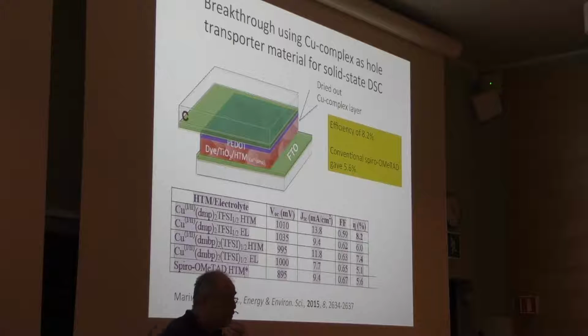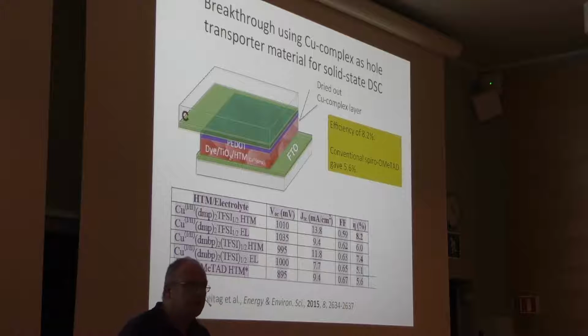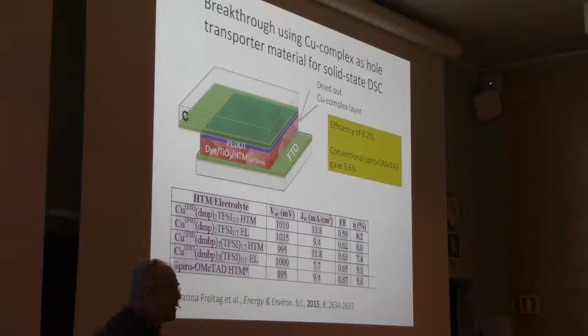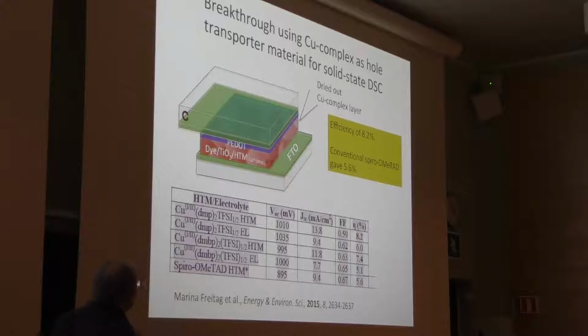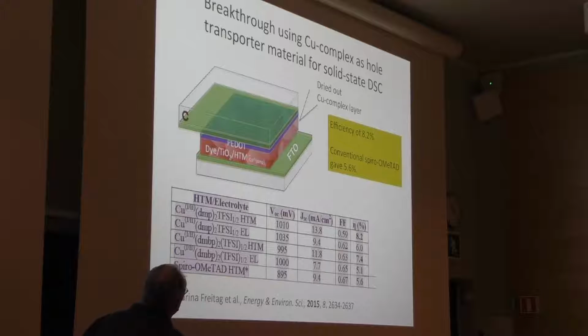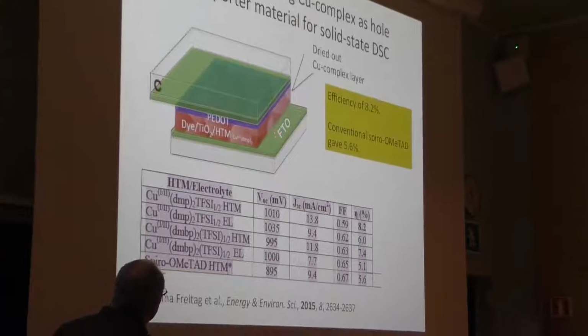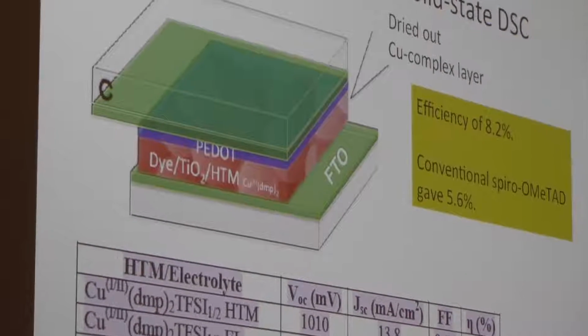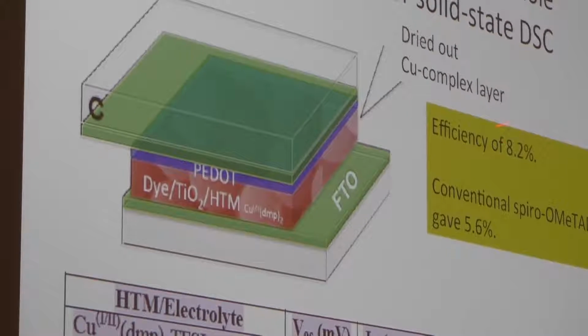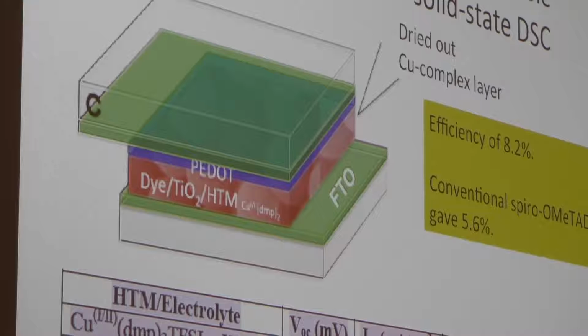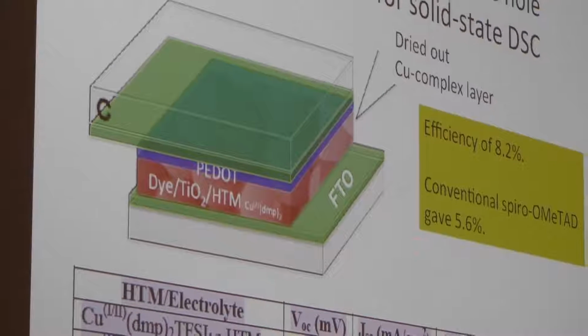Another bonus effect, which also was very unexpected with the copper, was that when you work with dye-sensitized cells, it's normally a liquid electrolyte, and the problem is then to seal them, because the solvent evaporates and it leaks, and it's all kind of practical problems. And when a solar cell has leaked electrolyte, it's normally dead, doesn't work. I don't know really why, but we had these dried out copper liquid systems, and the technician in Uppsala, I think he had nothing to do really, so one Friday afternoon or something he took this dried out cell and measured them, and strangely it had higher efficiency than the liquid cells. So we are not really sure what this is, but it seems like a kind of solid state copper complex system. Dried out cells work as well as the liquid system.